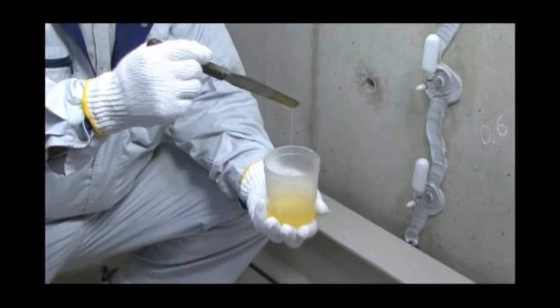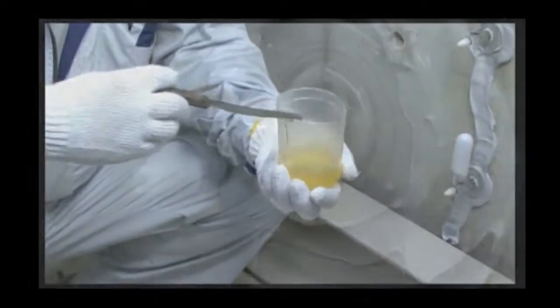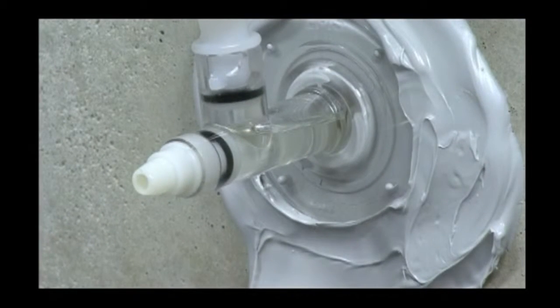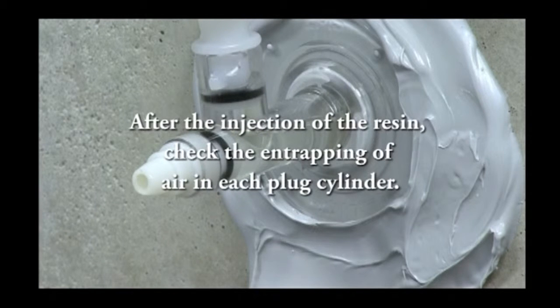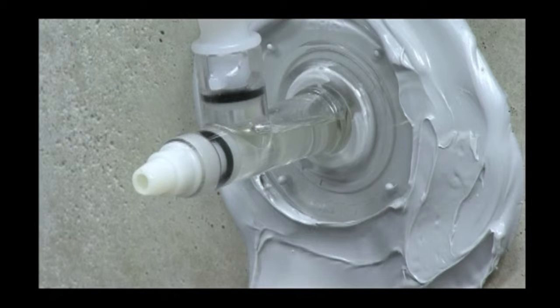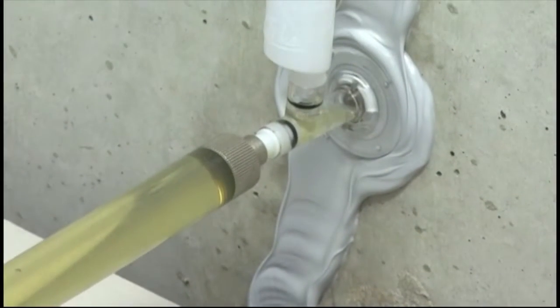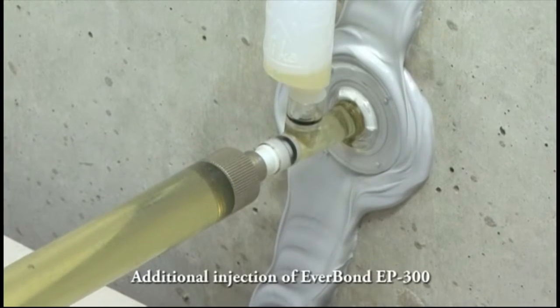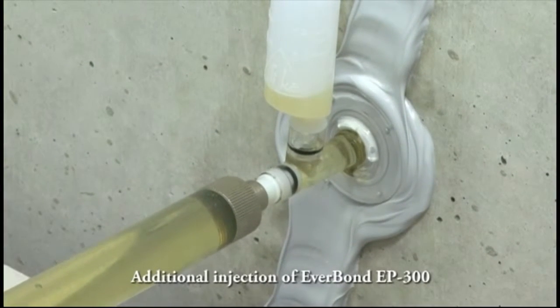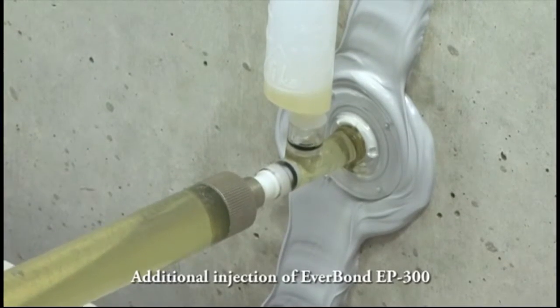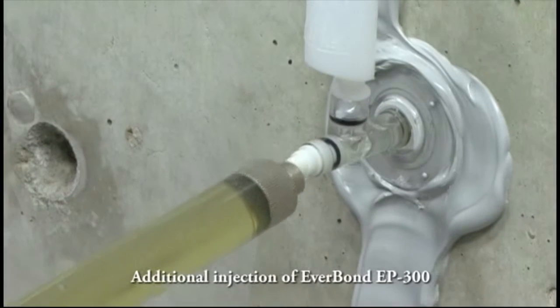To judge such a crucial point, check whether there is any air entrapped in the plug cylinder. If there is air, we should judge that the epoxy resin is not properly filled in. Here, if we assume that the viscosity still lacks, then fill in additional Everbond EP300 of low viscosity type. Since the plug cylinder is clear, you can check the resin gradually filling inside.